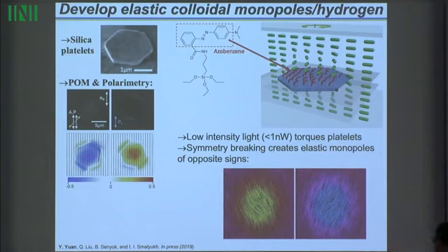Right, so you can see here, as we observe them between parallel polarizers in a microscope, these particles rotated in two different directions have different appearance, and with the help of polarimetry in the microscopic setting, we can also probe the polarization ellipses of light on a pixel-by-pixel basis as it passes through a liquid crystal with such a microparticle within it.